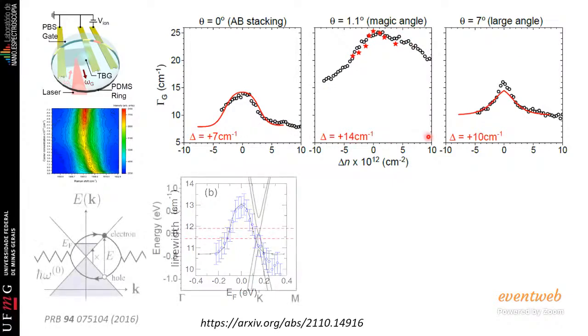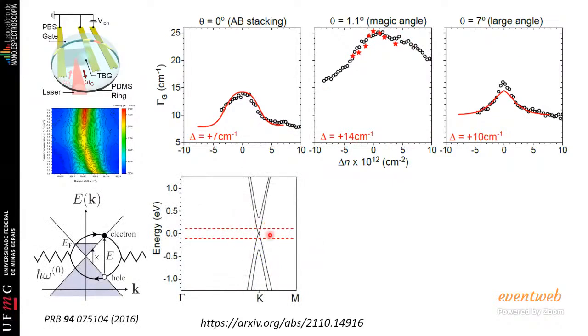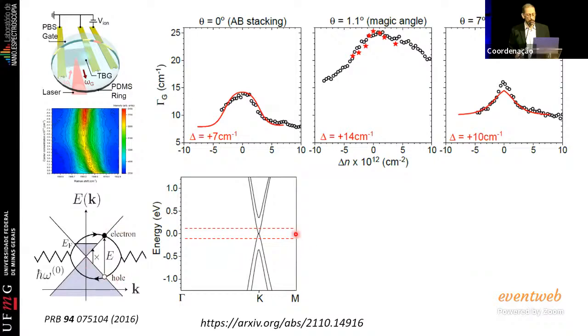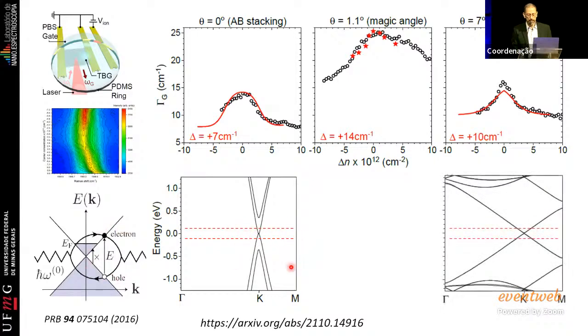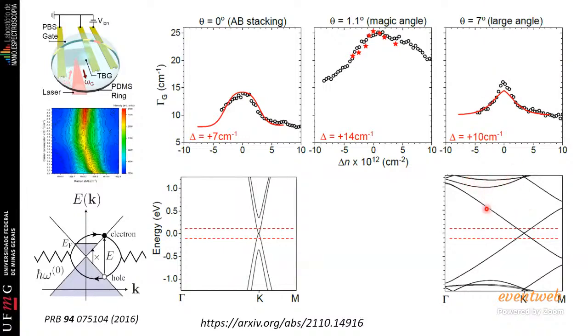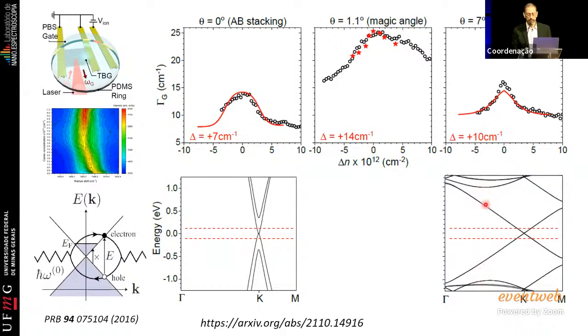And you can understand this when you look into the electronic structure. So this effect might happen here. This effect also happens there on the large angle. So again, we have this here that generates these absorption peaks, but at the very small range in the transport situation, what you have here is very similar to what you have there, but not at the magic angle. At the magic angle, you have the flat bands, and you have a very heavy folding that generates a special